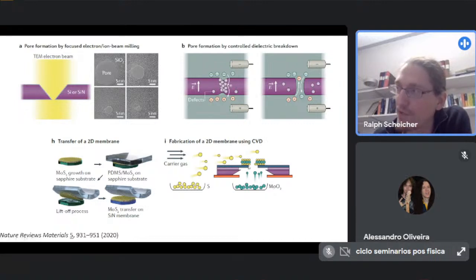Or you can start with a nanopore in some kind of a, for example, silicon nitride membrane, and then grow, through a process called chemical vapor deposition, CVD, the two-dimensional layer on top of this larger nanopore, this support here basically, and then control the process in some way that you stop before the gap is closing, or you can completely grow a 2D layer here and then you can open it with the help of some electron beam, for example. So these are different ways to create this kind of solid state nanopores.